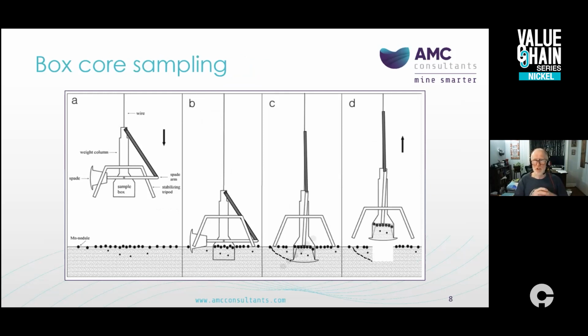For mineral resource estimation, better quality samples are preferred to increase confidence in the results. The box core is currently the sampler of choice. A steel sample box, open at both top and bottom, is lowered on a winch to the seafloor. This can take several hours, so it's less efficient than using the freefall grab sampler. The box cuts into the soft sediment under its own weight. When in position, the steel spade arm is released, and it swings under the box core to lock it closed. The box core is then winched back to the ship. The complete cycle may take 4 or maybe 5 hours, and only after the box core has been retrieved can the next box core be deployed.